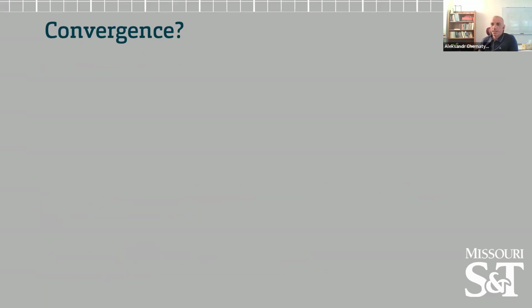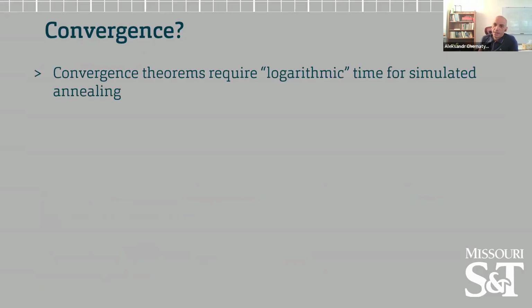Convergence. By convergence, I understand the question of whether we actually, with any certainty, can tell that we found the lowest energy structure. Again, as I already mentioned, convergence theorems require logarithmically divergent time with the size of the system, which basically means that in the simulated annealing scenario, the temperature has to be lowered slowly enough so that you would be sitting in the lowest attraction basin of your system. That should be a logarithmic decay in time due to the Boltzmann distribution, of course, that's typically used in simulated annealing. The problem is that it takes too long, and realistically, nobody can afford this kind of scenario.